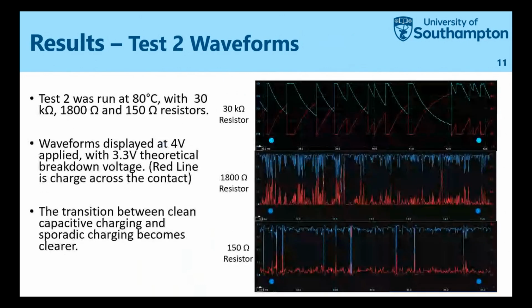For test 2, I was able to refine it a little bit, and ran the same scenario apart from increasing the temperature to 80 degrees, using resistors that were slightly closer in value, just to better show the transition between these two scenarios.